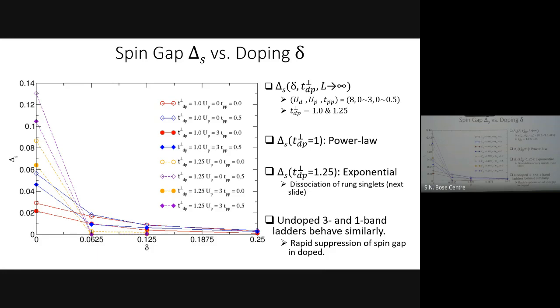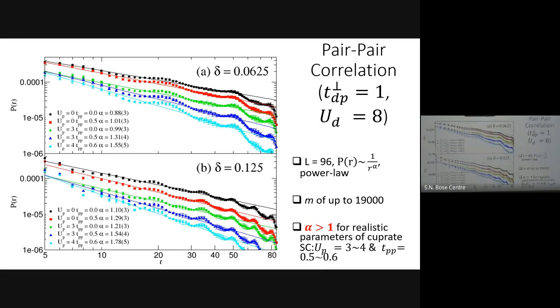So there are various parameters we work with. We work with TPP 0, so oxygen hopping, TPP 0.5, etc. Without going into details, basically TPP increases the spin gap here, but decreases the spin gap here. The UP, U on oxygen, decreases the spin gap here, and decreases the spin gap here. Both UP and TPP severely diminish the spin gap here. So what does it do to the pair-pair correlations?